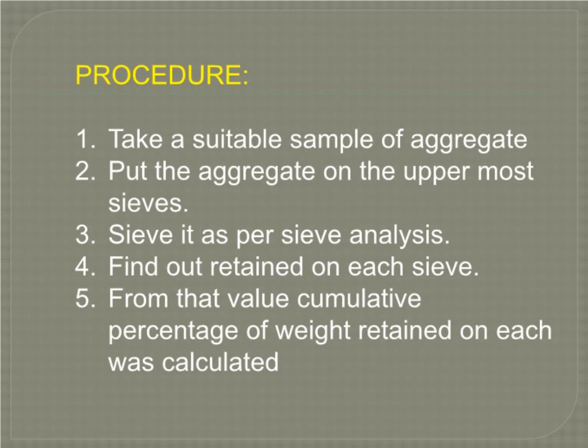Procedure: Take a suitable sample of aggregate, put the aggregate on the uppermost sieve, sieve it as per sieve analysis, and find out the weight retained on each sieve. From that value, the cumulative percentage of weight retained on each sieve is calculated.